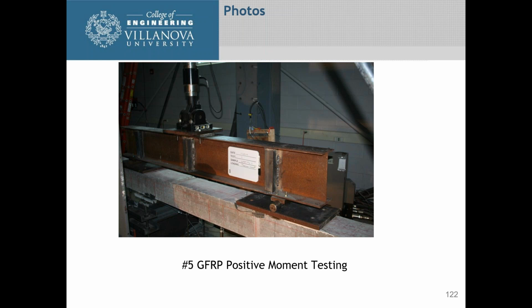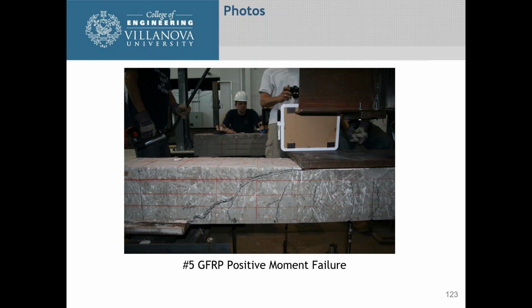Now, as I said, we did some additional testing for positive bending, and you can see here's the wheel closer to the center, and we put this more at the point of positive bending where we're applying the load. And here again, you can see what the failure was.